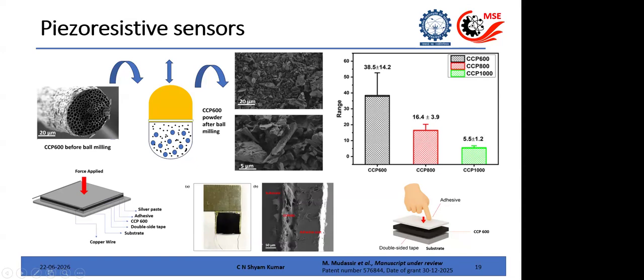You have a substrate, PET or something, a flexible substrate. Then you put a double-sided tape on that. Then you spread this CCP600, we call it, a sample that is pyrolyzed to 600 degrees Celsius. Then you connect it with two copper wires, and on the top you put adhesive to protect the powder. We use Fevicol. Okay, so maybe we can think of something like a 10 rupee sensor. And this sensor works. And the trend is the same actually.